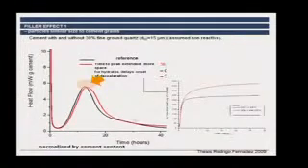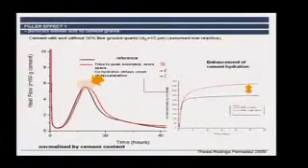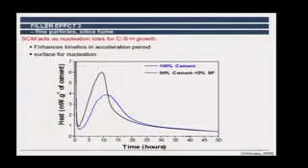And because of that, we see this extension of the reaction longer after the peak, and then slightly higher reaction thereafter. And in terms of the cumulative reaction, we can see this translates into quite a bit of extra hydration of the cement. So you can get to higher degrees of reaction of the cement purely by the fact you've got this inert material which is giving it more space to react. And typically it amounts to about 5%.